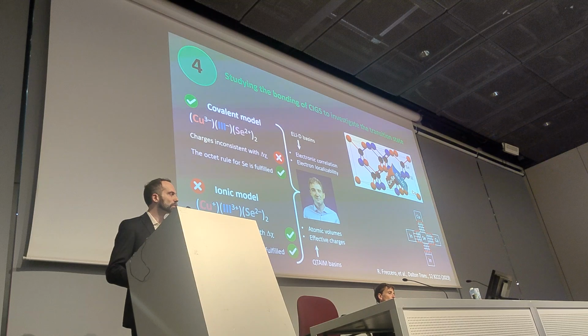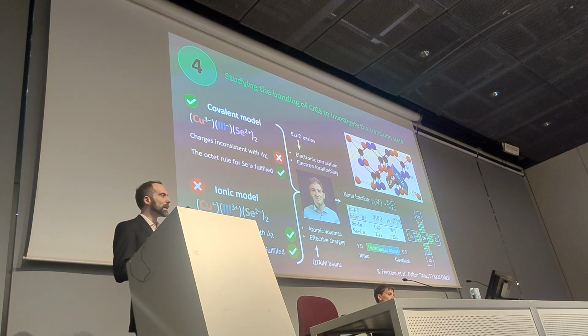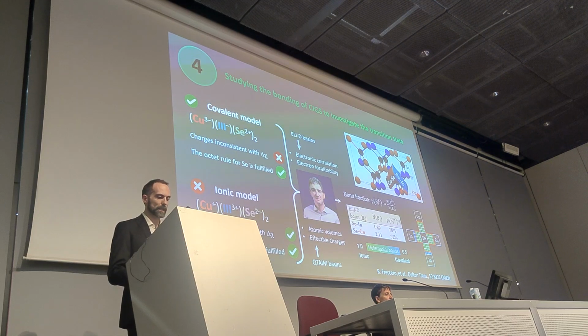Now, by crossing these two information together, we also can estimate, quantify how much of an ionic versus covalent character these two bonds correspond to. And we see that selenium copper is much more ionic than the selenium indium.